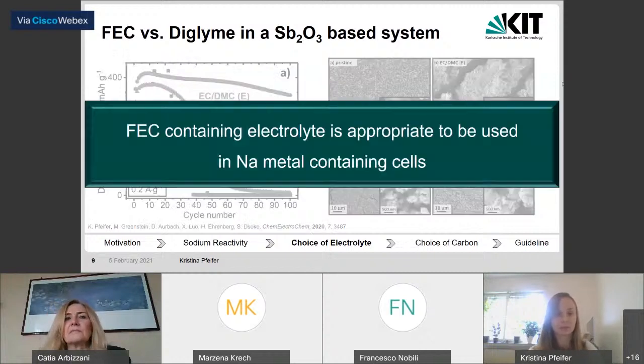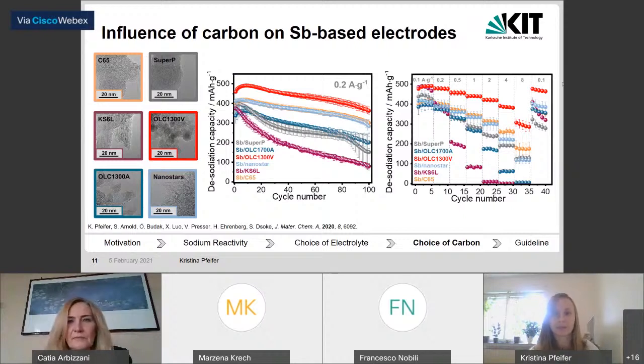That brings us to the conclusion that FEC-containing electrolytes are appropriate to be used in cells which contain sodium metal, and they also stabilize the working electrode. The next thing we looked at was the influence of carbon on antimony-based electrodes, using the knowledge we had before, so using the FEC-based electrolyte. What we see here is that the carbon really affects the performance of antimony-based electrodes. Depending on the chosen carbon, the rate capability and the performance can be really altered.